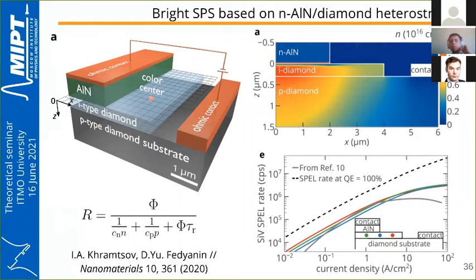Eventually, we have proposed the diode that you can see on the side, and found out that the electron density in the I-type diamond can be more than 10 to the 16 per cubic centimeter. At the same time, that is 2 orders of magnitude higher than can be obtained in the superinjection effect. At the same time, the hole density in this region is also very high, 10 to the 16 per cubic centimeter.